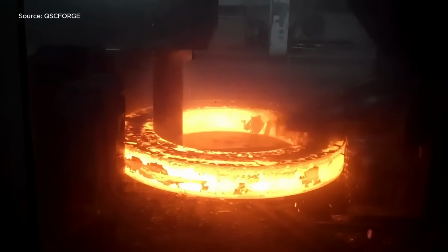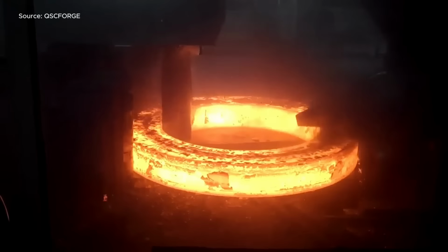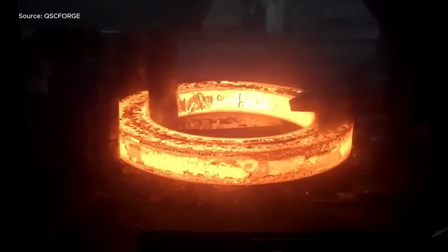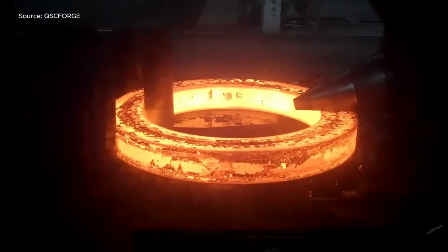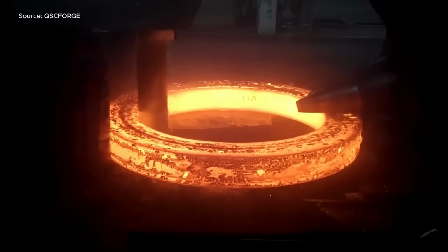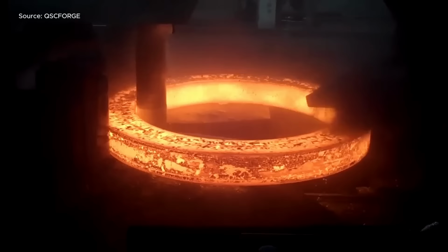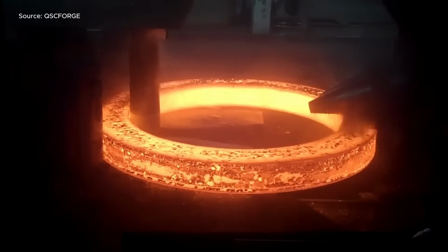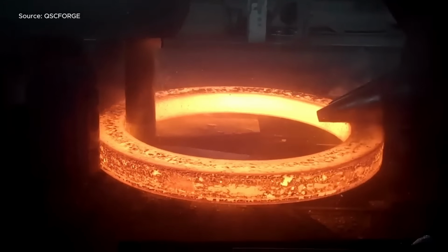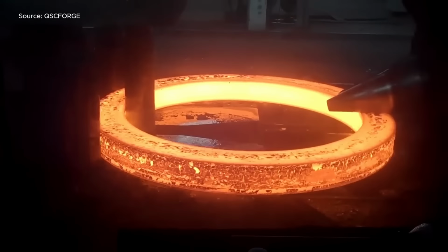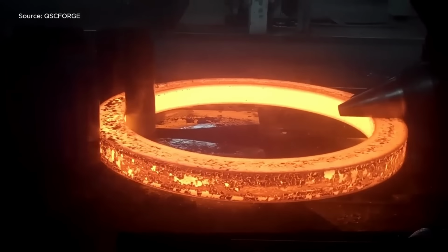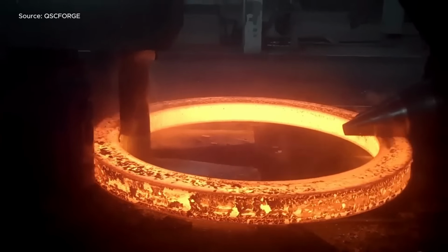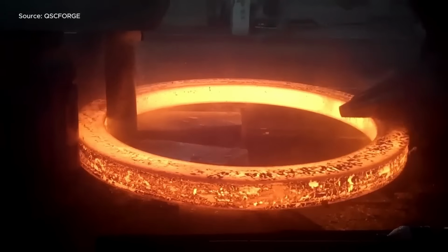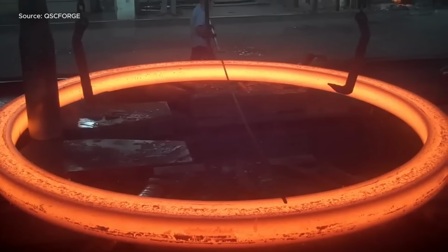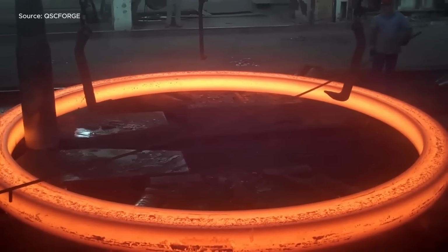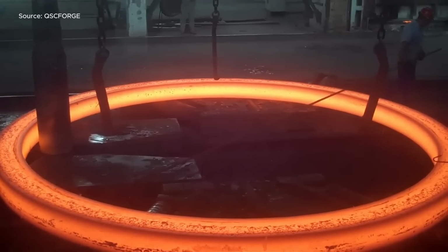At QSC Forge, the critical step in producing high-performance rolled rings is the ring rolling process, where radial axial ring rolling simultaneously compresses the ring radially, reducing wall thickness, and expands it axially, increasing the diameter. The machine is equipped with CNC control systems to ensure precise adjustment of rolling forces, rotation speed, and ring geometry. The rolling process also allows for tight tolerances, minimal material waste, and uniform mechanical properties throughout the ring. This precision forming technique enables QSC Forge to produce rings up to several meters in diameter for demanding applications.